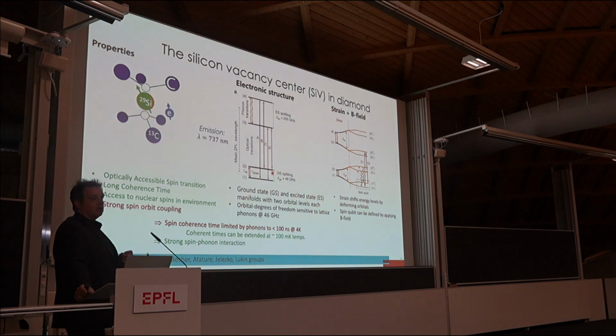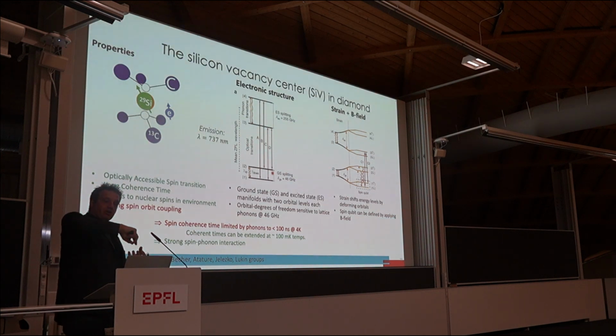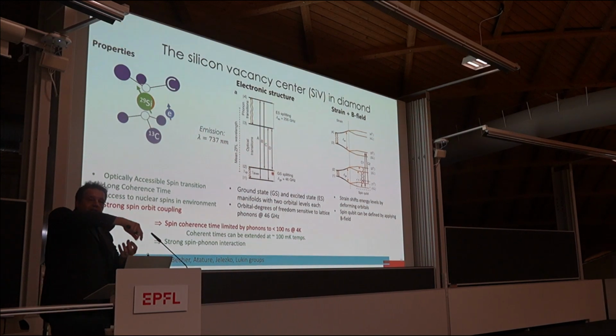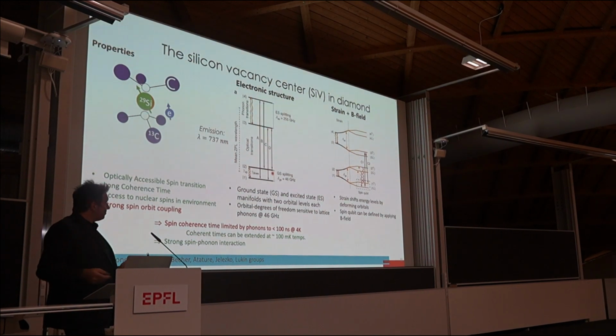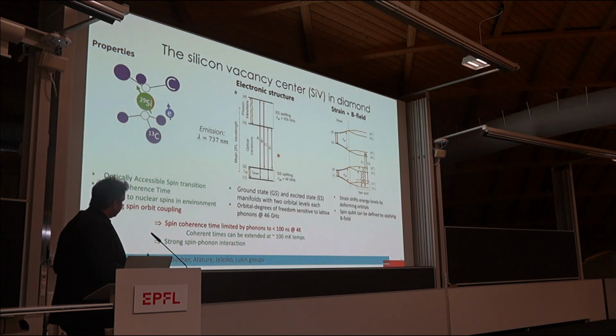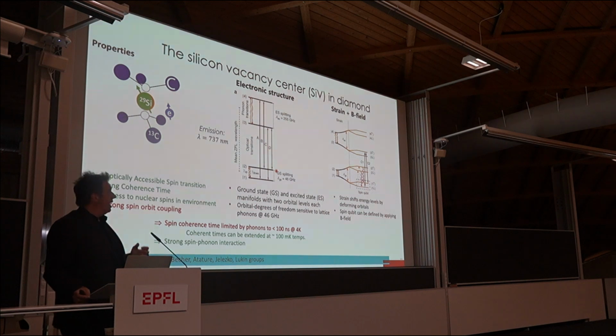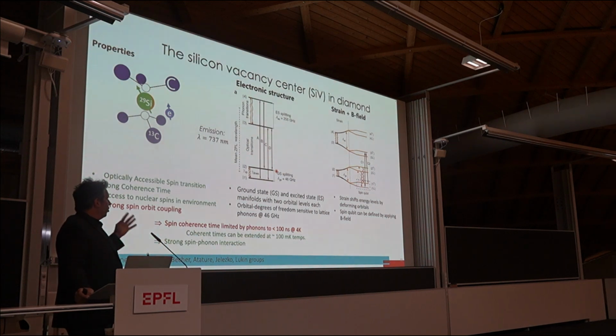And because of the really strong coupling between spin and orbit, and if you haven't heard this term, you can think about it in the context of this kind of wrong quantum model of an atom, where you have an electron circling around the nucleus and it's spinning. So the orbital magnetic field and the spin magnetic field interact. And that causes phonons to decohere the spin. And so in order to fix it, you cool it down.